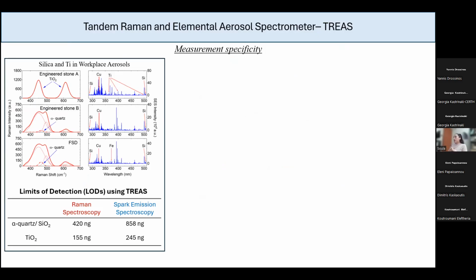First, we used it to identify and quantify some compounds of interest for NIOSH, which are the silica and the titanium dioxide. We used two different engineered stones and fracking sand dust. In the first case, we see the two characteristic peaks. The red lines are the Raman spectra, and the blue lines are the spark-emission spectra. So in the first case, using the Raman spectra, we see the two characteristic peaks that we get when we have the titanium dioxide. We also see the titania in spark-emission spectroscopy, along with some other elements.